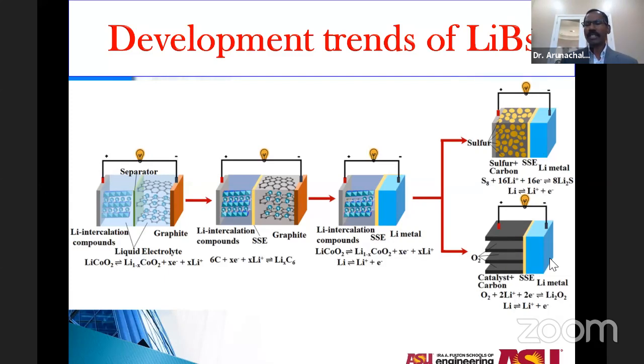So lithium has an extremely high electrochemical equivalence, 3.86 ampere hour per gram, and the air electrode has an unlimited amount of active material, oxygen from the atmospheric air. So this could actually lead to closer to, or well above, 1,000 watt-hour per kilogram as it develops with time. So that's a huge potential for these solid-state batteries in terms of energy density and also an extremely high level of safety.